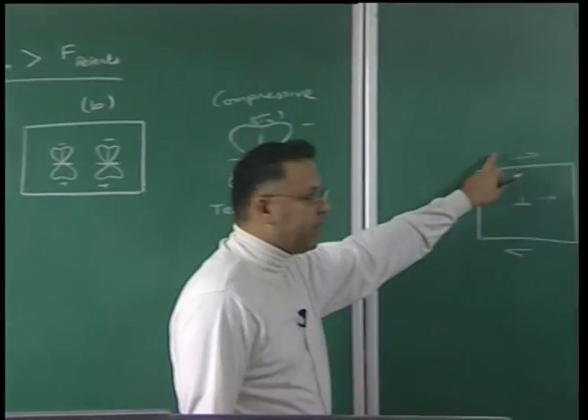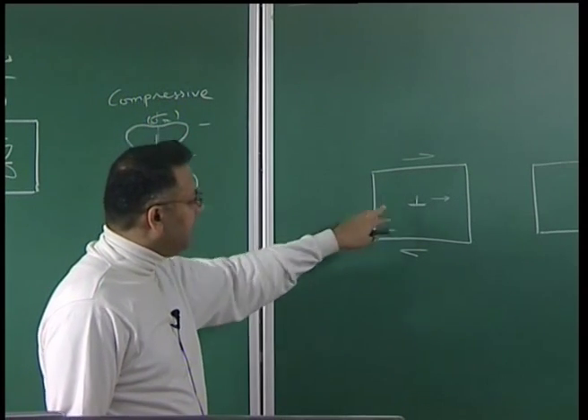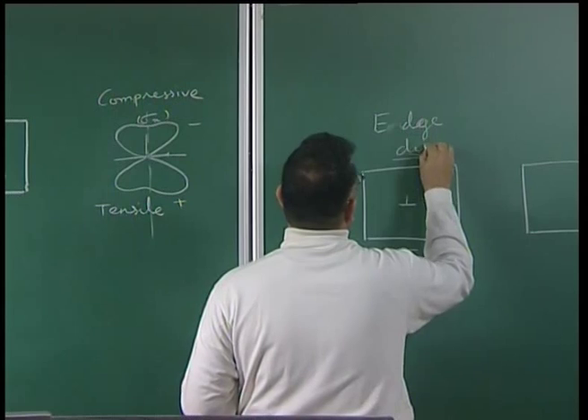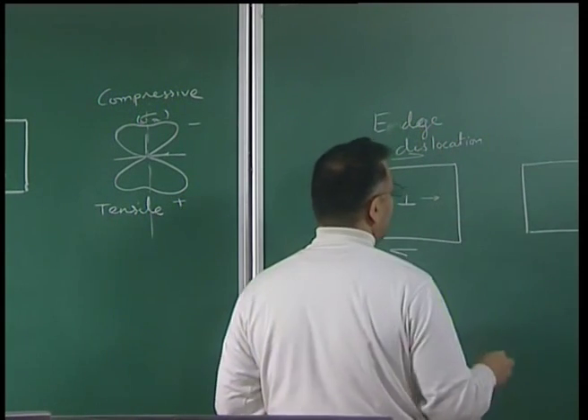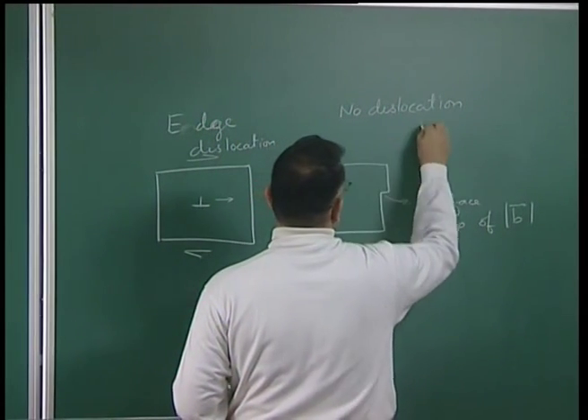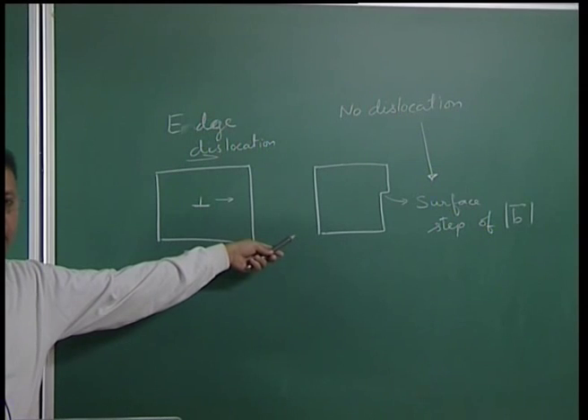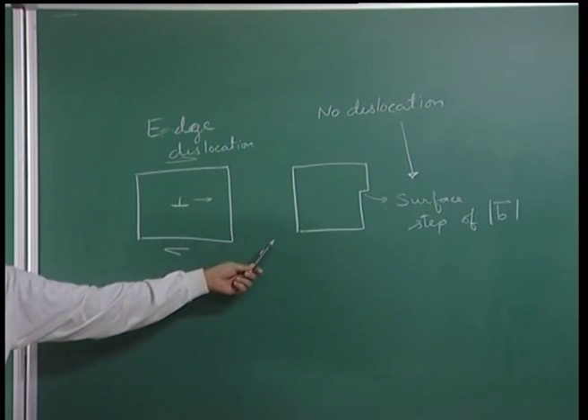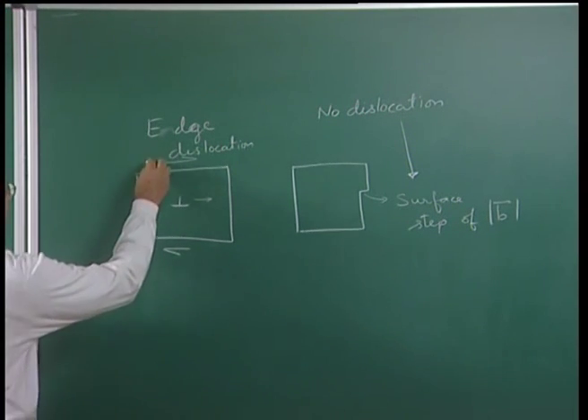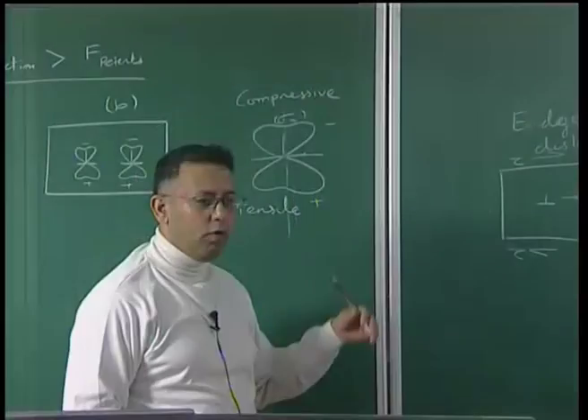When considering pairwise interactions, defects communicate via long-range stress fields, and we must also consider external stresses or constraints imposed on the system and their effect on the evolution of the defect structure. In the edge dislocation example, when the surface step forms, the long-range stress field of the dislocation vanishes — one defect has evolved into another defect, lowering the system's energy, mediated by an externally applied shear stress tau.